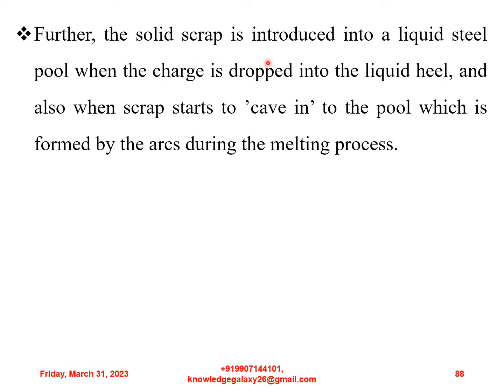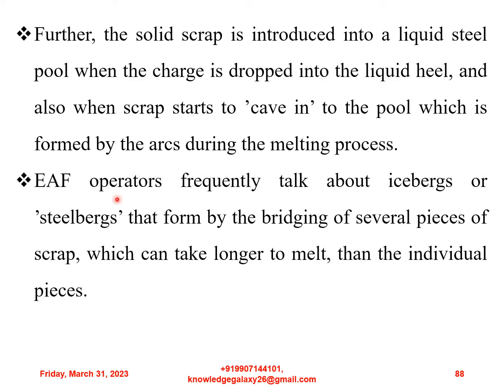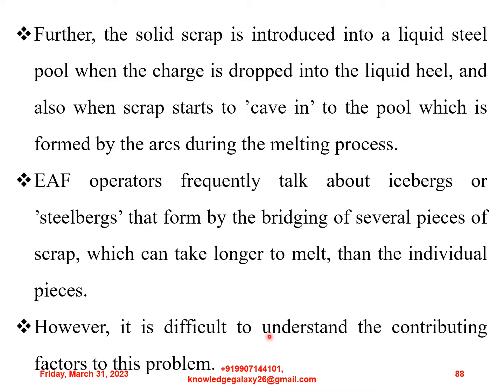Further, the solid scrap is introduced into a liquid steel pool when the charge is dropped into the liquid heel and also when scrap starts to cave in to the pool which is formed by the arcs during the melting process. Electric arc furnace operators frequently talk about icebergs or steel bergs that form by the bridging of several pieces of scrap, which can take longer to melt than the individual pieces. However, it is difficult to understand the contributing factors to this problem.